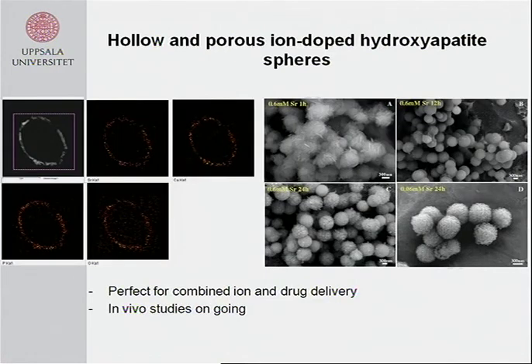And then I would like to come back to these ion substituted HAs, which we have big hopes for. These are just electron micrographs showing a cross section of one of these. We call them nano HA, but they are in the size of 100 nanometers to 1 micron in diameter. But they're perfectly hollow. So what you see here are maps of calcium and phosphorus. And these are suitable for loading and release of active substances. And they also have a slow release of the ionic species in vivo. And there are in vivo studies ongoing on these as well, which are unpublished at the moment.